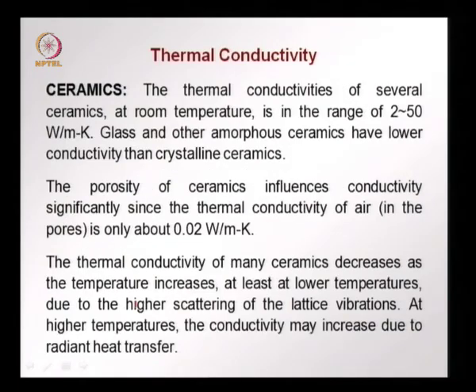In ceramics, we find that thermal conductivity has a wide range, say in the range of 2 to 50 watt per meter Kelvin. Glasses and some amorphous ceramics have lower conductivity than crystalline ceramics, again as the packing increases, conductivity becomes better. The porosity also influences the conductivity significantly, since the thermal conductivity of gases is very low, like the thermal conductivity of air is only about 0.02 watt per meter Kelvin, and in the pores of these ceramics we have air which is not facilitating the conductivity.